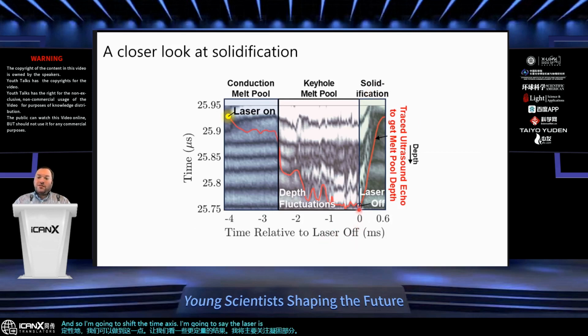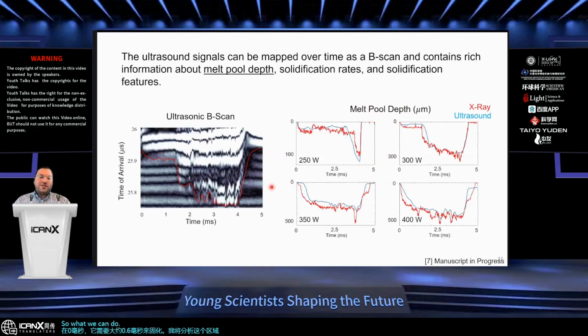I'm going to say the laser is off at 0 milliseconds, and it takes about 0.6 milliseconds to solidify. I'm going to be analyzing this region. So what we can do, simply, my student traces the perturbation to the earliest ultrasonic arrival, and we can get a line like this. We can plot that, right? So that's these blue lines in here.